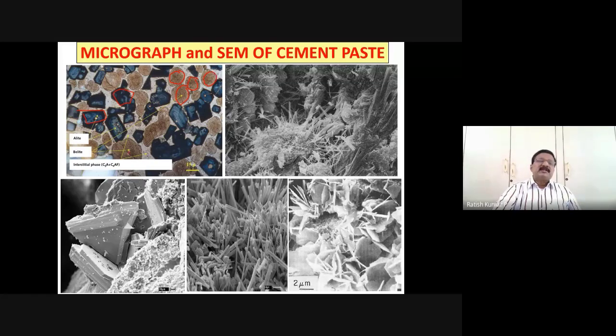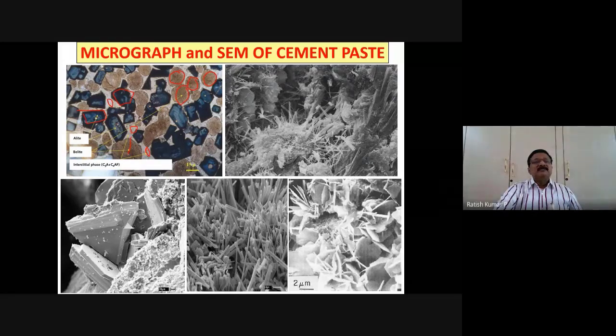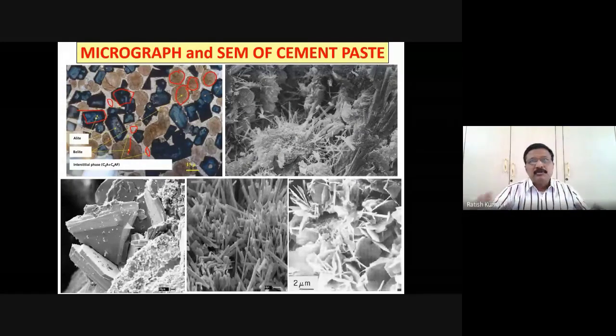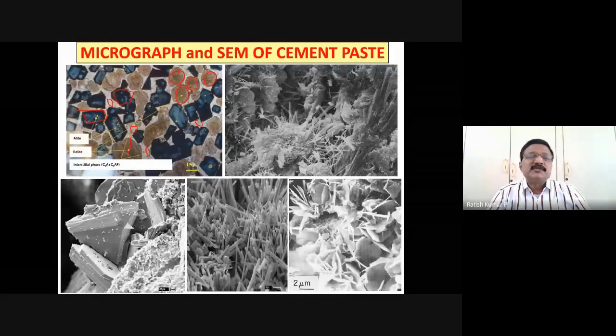And there is the interfacial transition zone, which is a ground mass area, where you can have the space between the belite as well as the alite phases, which is the tricalcium aluminate and the tetracalcium aluminoferrite. This is not the aggregate space. I'm talking about the microstructure, I'm really talking about the phases, that is alite, belite as well as the C3A and C4AF phases. So the ground mass can be identified between these areas, as you can notice here. These are the alite phases, and the round ones are basically the belite phases.